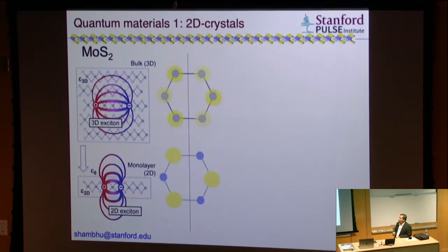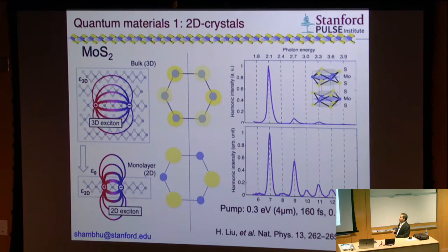So we took the example of MoS2 because it's a prototypical 2-dimensional crystal. This is the bulk, looking from the top of the crystal. Same thing here, but this is a single layer. You should be able to see the difference between the single layer and the bulk. The single layer does not have reflection symmetry or inversion symmetry in this plane. The bulk is basically an average of different layers, oriented by 60 degrees, but when you have so many layers, on average there is a reflection symmetry. That description is actually enough to explain the qualitative features of this spectrum.